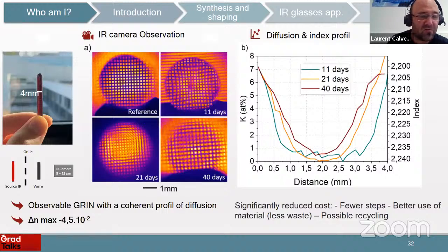So we made a glass of 4 millimeter diameter here. We used an infrared camera, an infrared source, and a grid here. So this is the base glass, and we can see that we are deviating the light when we are using the GRIN lenses here. And at the end, so just by using a flat glass and ion exchange, we are able to get new lenses, very flat and with a good curvature of the light.